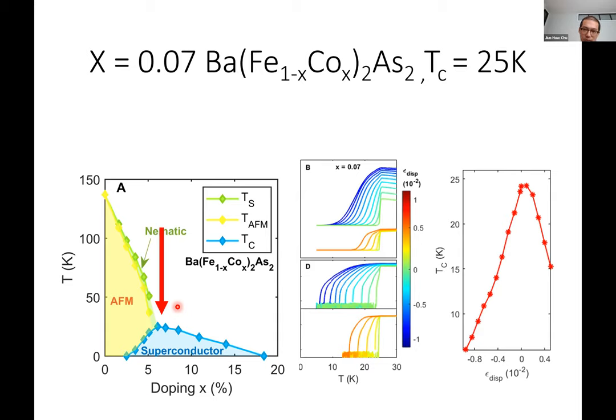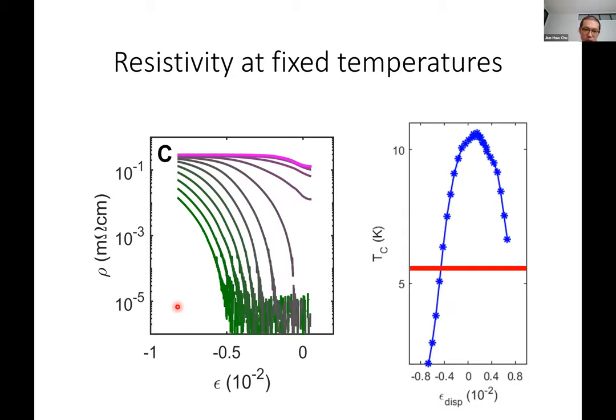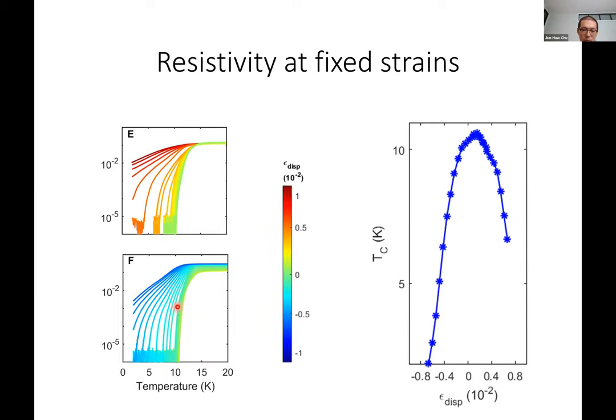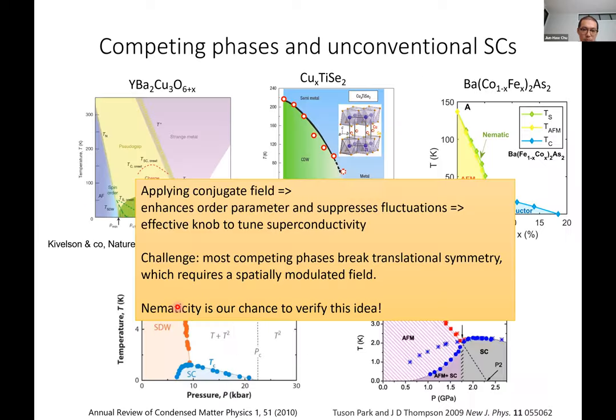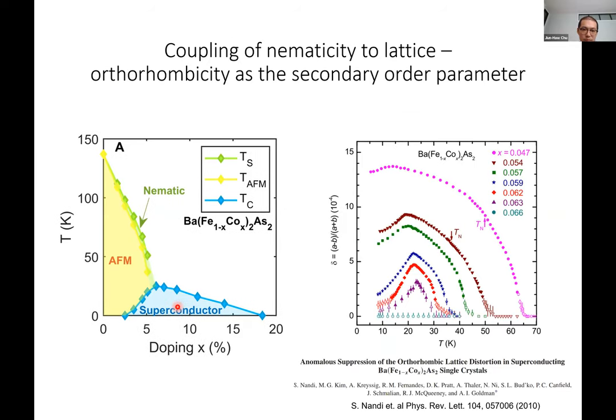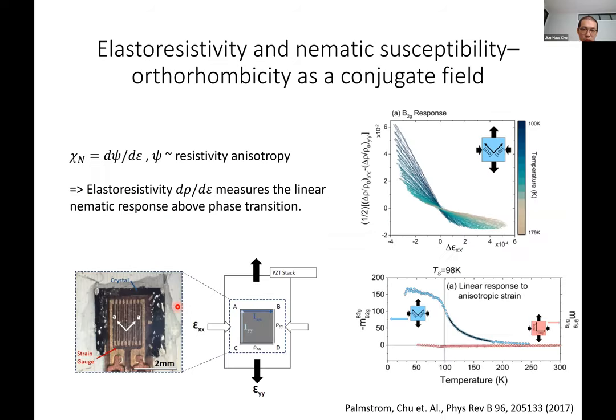And it is just the effect of, no, it can be the effect of the domain. So what do you attribute it to? It's not the effect of the domain. I think it's that the system is more resistive in the nematic states. This is the part that I haven't really talked about, but for example, this elastoresistivity curve I showed you, right? I showed you how rho xx minus rho yy responds linearly as a function of anisotropic strain.